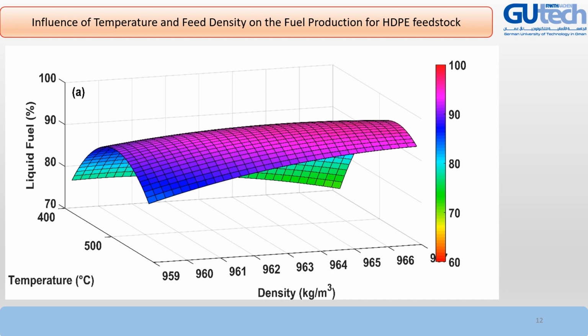The temperature range is from 415 to 585 degrees Celsius, and the density is 959 to 967 kg per meter cube. As you see, by increasing the temperature, the liquid fuel efficiency has increased, reaches the maximum, and then decreases. The maximum efficiency goes from 89.1 to 95.3 based on the feed density.